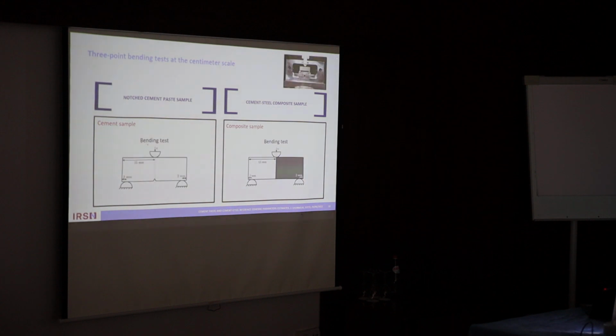So in order to estimate those parameters, I've considered 2 types of samples. The first one is a pure cement-based sample containing a notch, and the second one is a cement-steel composite sample, both samples measuring 3 cm long and having a cross-section of 1 cm square. I've tested these samples under 3-point bending tests, as illustrated here.